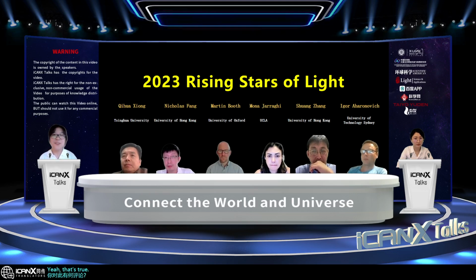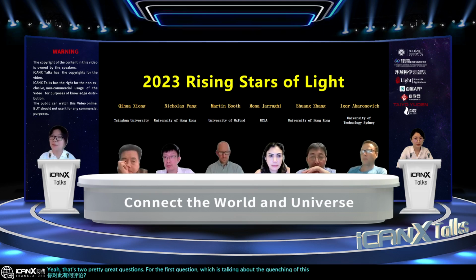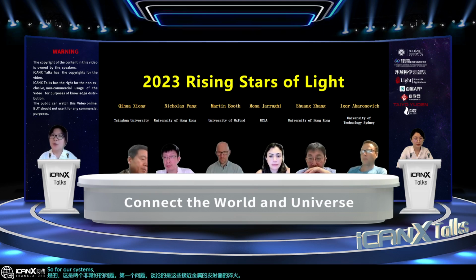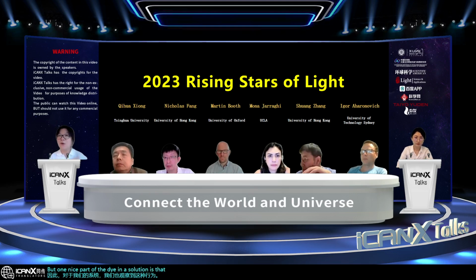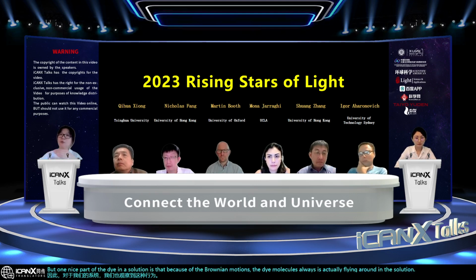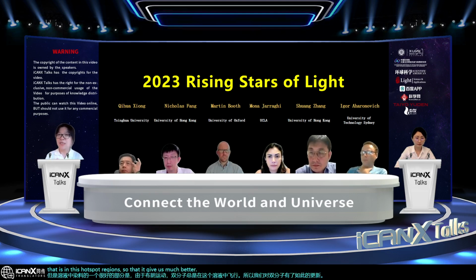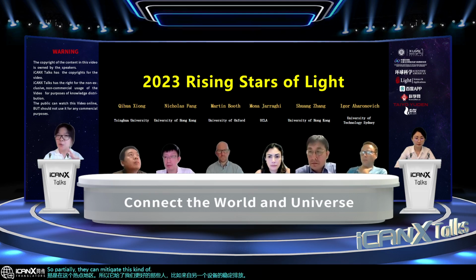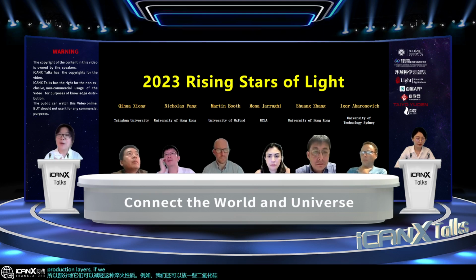Yeah, those are two pretty great questions. For the first question, which is about the quenching of these emitters close to metals, for our systems we also observe such behavior. But one nice part of the dye in a solution is that because of Brownian motion, the dye molecules are always flying around in the solution. So we have a refreshing of the dye molecules in these hotspot regions, which gives us much better, more stable emission from this lasing device. So partially it can mitigate this kind of quenching. For example, we can also put some silica protection layers if we worry about the nanometer-scale quenching of the emitters.